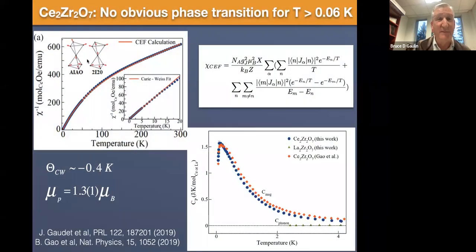And in due course, we did make materials, and we did a similar set of low temperature characterization to what the PSI people had done on cerium zirconate. And we got similar results. So this is showing you our magnetic susceptibility. Actually, it's the inverse magnetic susceptibility. It's what would be a Curie-Weiss plot as a function of temperature. But you see that, in fact, the inverse magnetic susceptibility is curved.